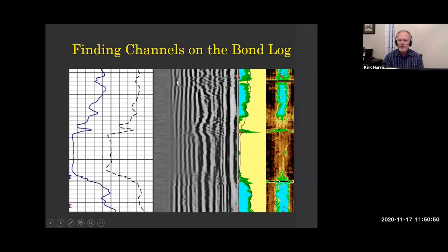Here we have good cement. Why do I get amplitude here and here? It's a channel. I know that because I compare it to the ultrasonic. And this gives you an indication quite often of when channeling occurs. When channeling occurs, you get brief spots of channeling and brief spots of good cement. Often that good cement occurs after a collar or a centralizer. If you have all one long bad channel, it's probably bonding, not channeling. They get abbreviated in the real wellbore. Just something to think about when you're trying to determine, do I have channeling instead of poor bonding on a bond log when I don't have the help of the ultrasonic.